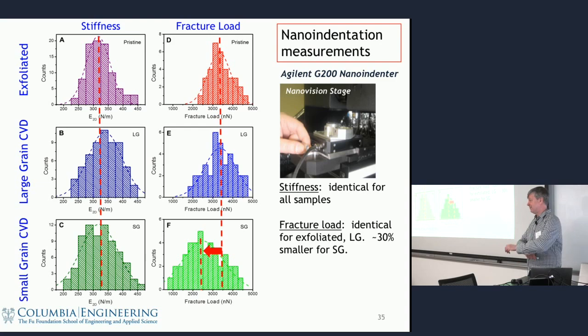This took some hacking of the nanoindenter system, because these nanoindenters are designed for pushing on solid surfaces, the surface of a metal, inducing indentations in the surface of a metal. So they can map surfaces and find the surface, but they're used to pressing pretty hard to do so. We had to train it to be a lot more gentle so it wouldn't just break all of our membranes as it was looking for them. But that can be done. And then we could make lots of membranes, map them, and do automated testing, and so really start to get some much better statistics.